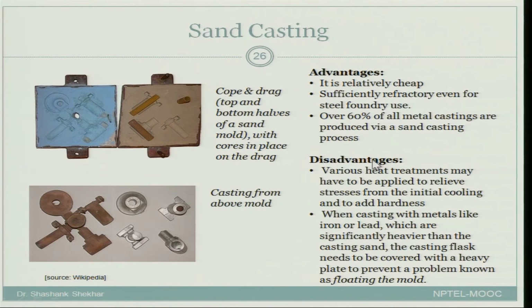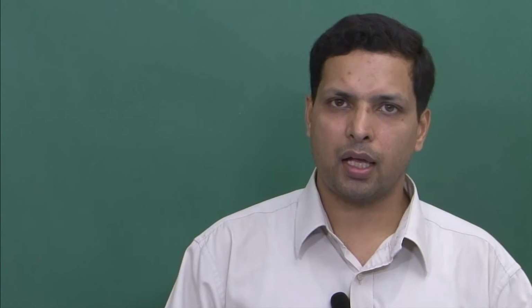But it is not that sand casting has only advantages, it also has some disadvantages. Various heat treatments may have to be applied to relieve stresses from the initial cooling and to add hardness. Once you do sand casting, because of the stresses that are generated on the surface, you may have to apply some additional heat treatments after the casting process is done, so that the stresses are relieved. If you do not relieve the stresses, then the component may have very poor properties, especially the mechanical properties. So additional heat treatments may be required whenever you are doing sand casting.